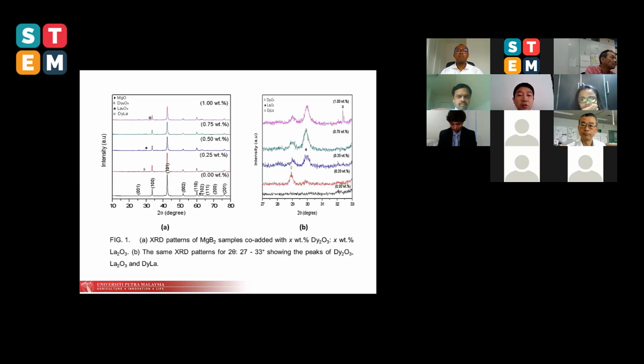The XRD patterns show that we have formation of some impurities, especially if you look at the peak here. That is actually unreacted lanthanum oxide, unreacted dysprosium oxide, and also a dysprosium lanthanum phase. However, when we calculate the intensity of those impurity peaks, we notice that their intensity is actually quite low compared to the intensity of MgB2 peaks, indicating that the amount of those impurities may not be that great.